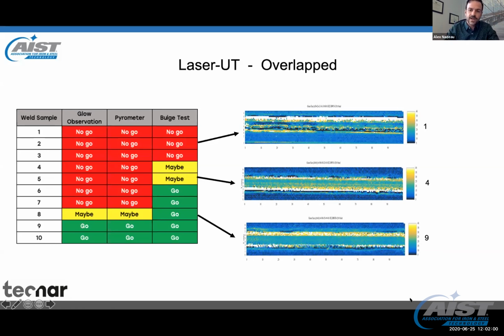But if you look at the UT testing, the UT testing actually was in better accordance with the bulge test. We could see very fine recrystallization for the green welds. The ones that could maybe have passed through the process were showing some irregularities, and we could also be in accordance with the no-go ones that were actually very badly welded.